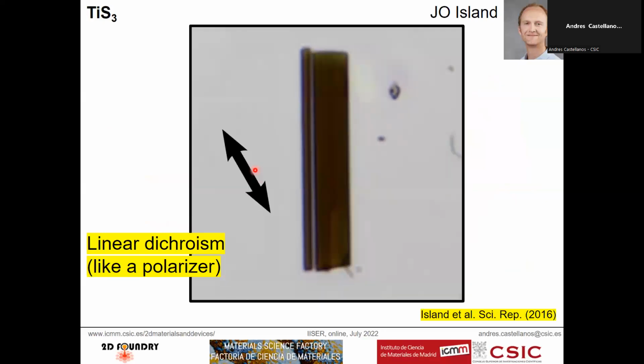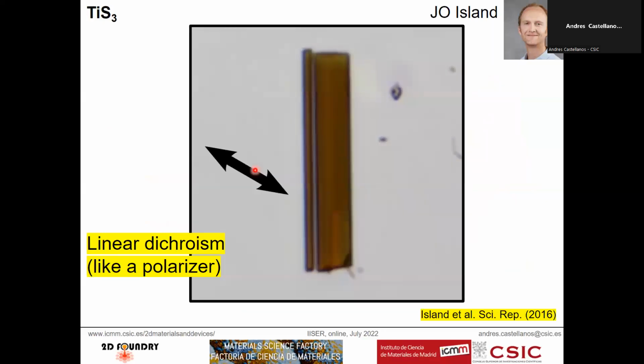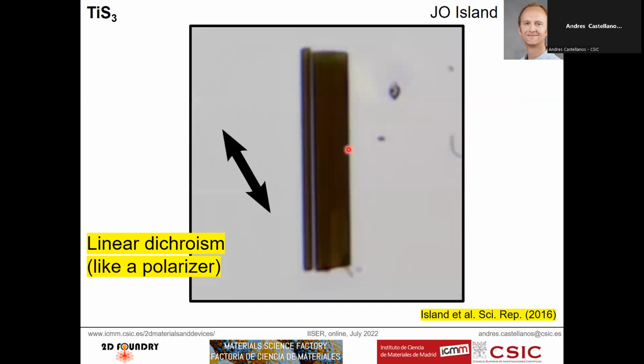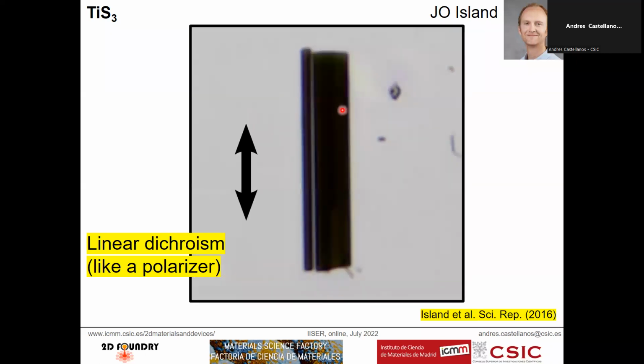Regarding the anisotropic properties of this titanium trisulfide, one of the easier things that you can do in the lab is take one of these flakes exfoliated by mechanical exfoliation, put it on a transparent substrate, and start taking pictures in transmission mode in an optical microscope. If you use a linear polarizer underneath and start rotating it, you see how the transmittance of this titanium trisulfide changes with the alignment of the linear polarization angle with the crystal direction of the flake. The elongated direction of these flakes is the B axis of the crystal. When the light is polarized parallel to the B axis, the flake becomes dark, so it's very opaque. When the light is perpendicular to the B axis, it's much more transparent.